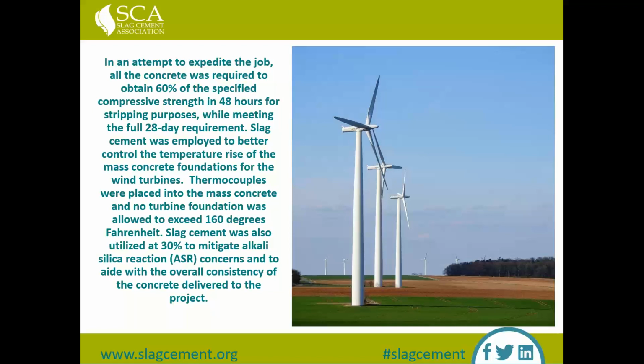The slag was employed to better control the temperature rise of mass concrete for the foundations. They placed thermocouples into the mass concrete and made sure that no foundation allowed temperatures in excess of 160 degrees Fahrenheit. They also used slag cement at a 30% substitution rate to mitigate alkali silica reaction and to aid with the overall consistency of the concrete used on this project.